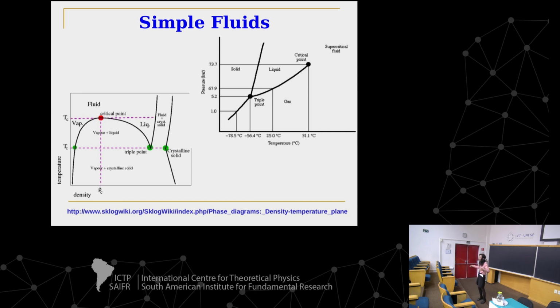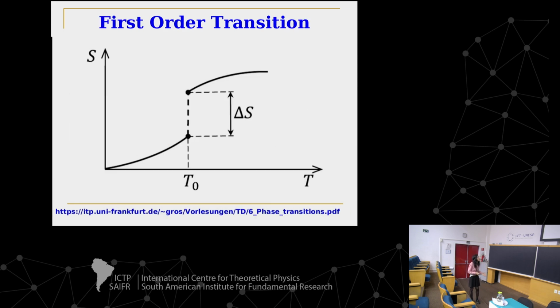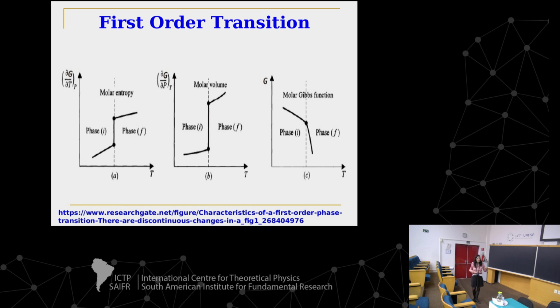We call it first order because I have a jump in the density. The density on one side is one value, the density on the other side is another value, which means that the density has a jump in value. So in this first order transition, you also have a jump in the entropy. And the Gibbs free energy in this region is continuous. It has this shape because thermodynamics implies that when you have the Gibbs free energy against temperature, it has to be this shape. But as you see, the slopes of these sides are different.